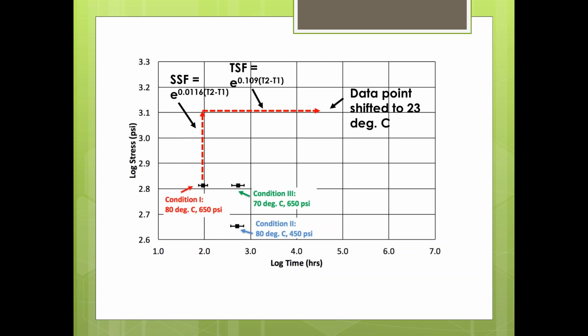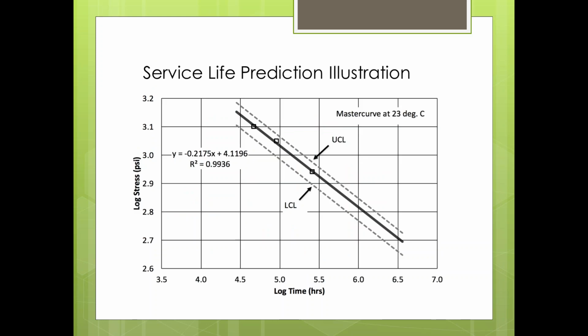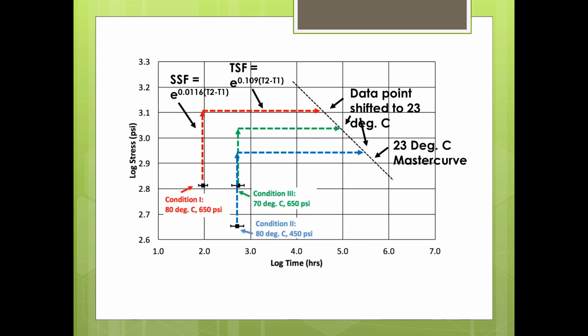So once you have those 3 test conditions, you use what's called a stress shift factor and a time shift factor to shift the data points to an ambient temperature or a representative temperature. In the research, they utilized 23 degrees Celsius, which is very conservative from the standpoint that the southern states like Florida or Texas will likely see ambient temperatures in the ground, soil temperatures in the ground closer to this 23 degrees Celsius mark. In a lot of the northern states, you'll obviously see a lower ambient temperature just naturally because of us being in a far northern latitude.